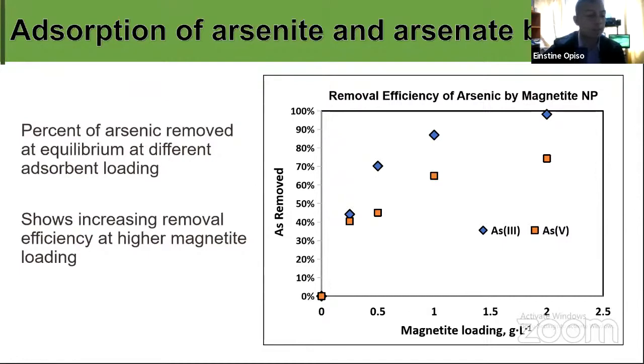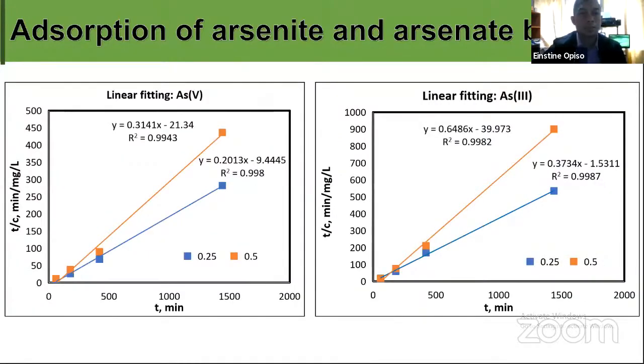And we also did the linear fitting of the adsorption of arsenite and arsenate by the synthesized magnetite nanoparticles. The linear fitting results show that the trend follows pseudo-second order kinetics, and in comparison between arsenite and arsenate, the slope of arsenite is much higher compared to arsenate.